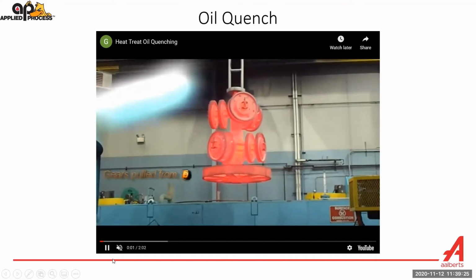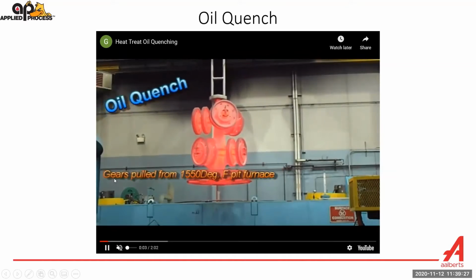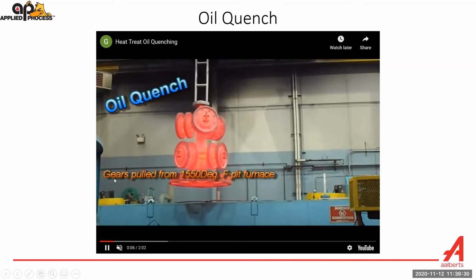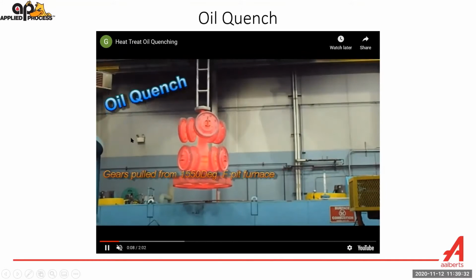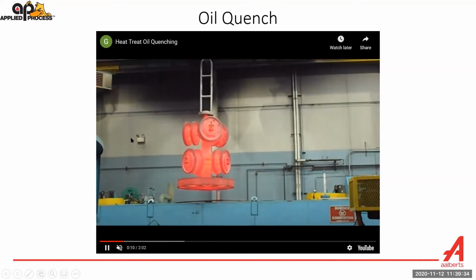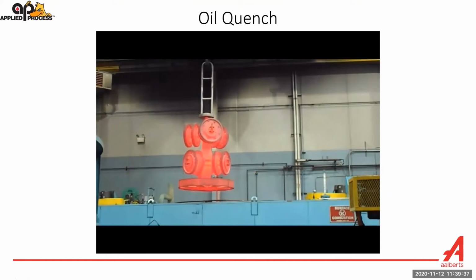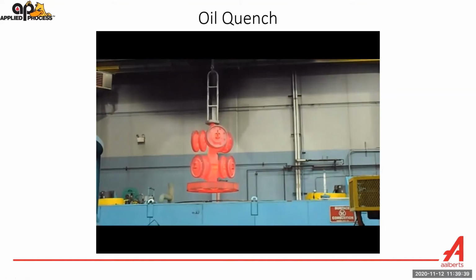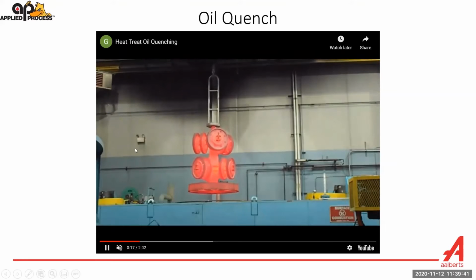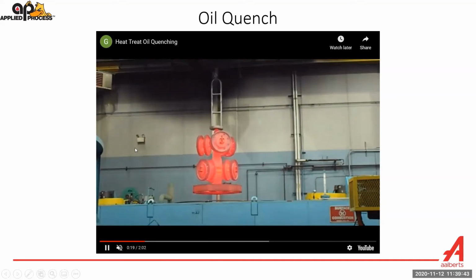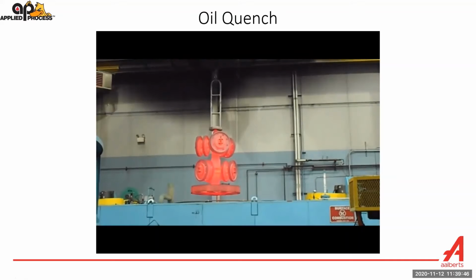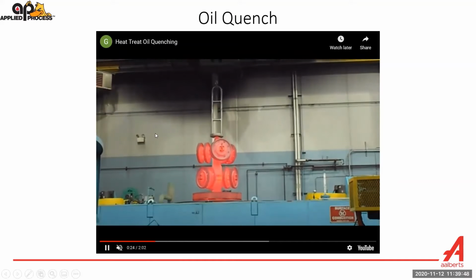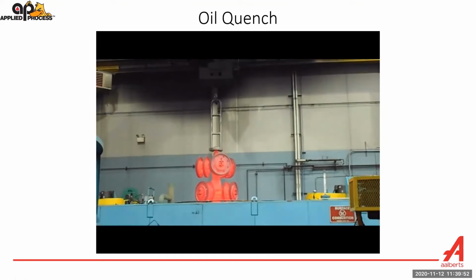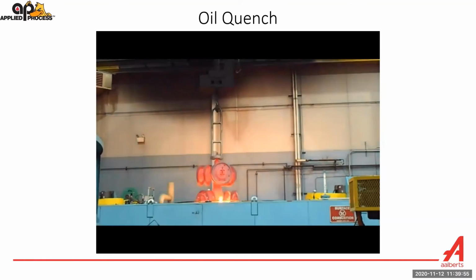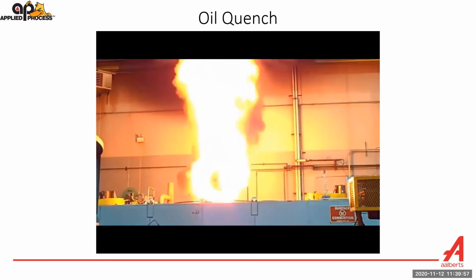So here we can see some parts over an open oil quench tank, red hot, about 1550 degrees Fahrenheit. Now, the interesting thing about this is that the parts are oxidizing and they're cooling at this point in time. So that's actually something bad when you come out into open atmosphere. And as the parts hit the oil, you will see flames erupt.